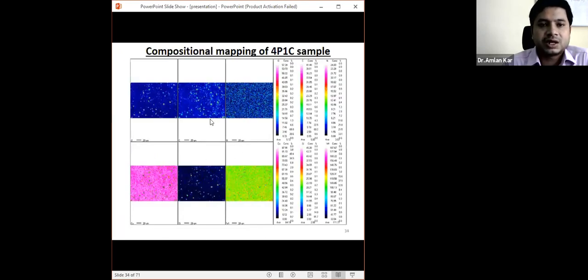And from the compositional analysis you can see that this is a homogeneous distribution of the particles. This is 20 micron, this is almost a 100 micron by 150 micron sample. From there you can see easily that even in the big sample, the homogeneous distribution of the second phase particle, which is SiCN, can be clearly visible. So this is a fabrication of homogeneous ceramic matrix composites, which has been derived from the polymer